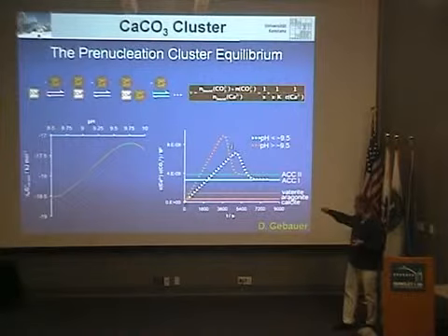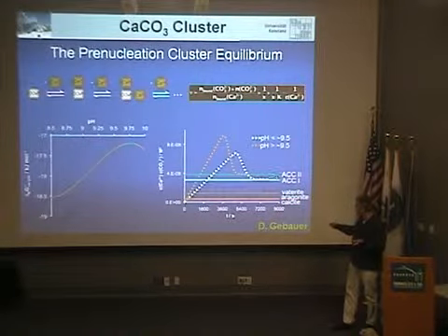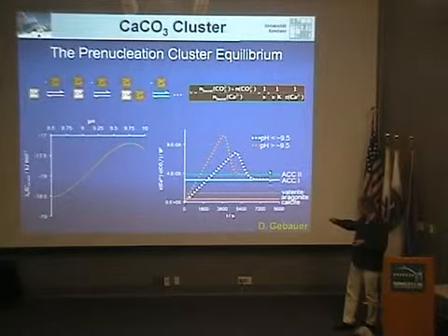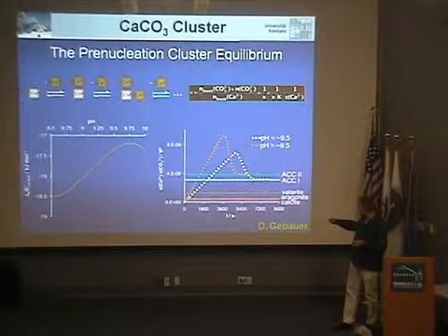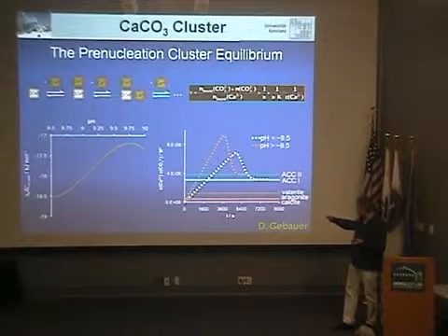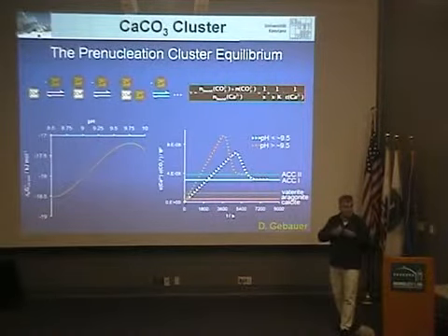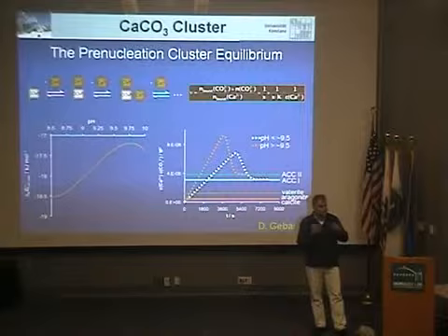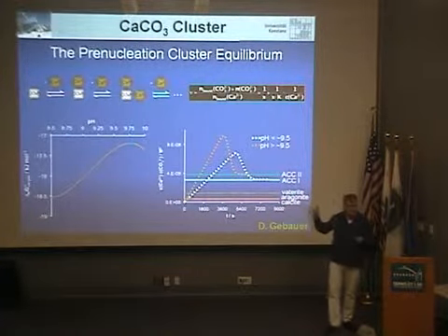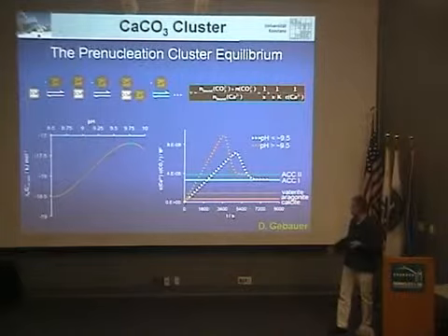And here are the titration curves plotted. And if you look at the solubility products, which you have here, compared to the crystalline polymorphs, you see that they clearly differ. So at the lower pH, I have a lower solubility product. This is amorphous calcium carbonate 1. And at a higher pH, I got more soluble species. And usually, if I got different solubilities of particles or species, that hints at different structures, although these clusters are certainly amorphous or X-ray amorphous.